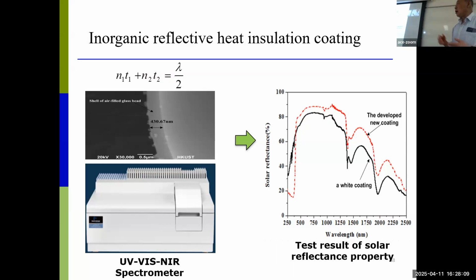This reflecting material we developed according to this refraction equation. So we have N1 T1 plus N2 T2 equal to lambda over 2. N is the refractive index of material, T is the thickness. So when we design the material, if we have many layers, we can reach this formula, and the wavelength lambda cannot penetrate. We did this reflection test, and you can see the red one is the material we developed. Basically it reaches about 90% reflection for the range from visible to infrared.